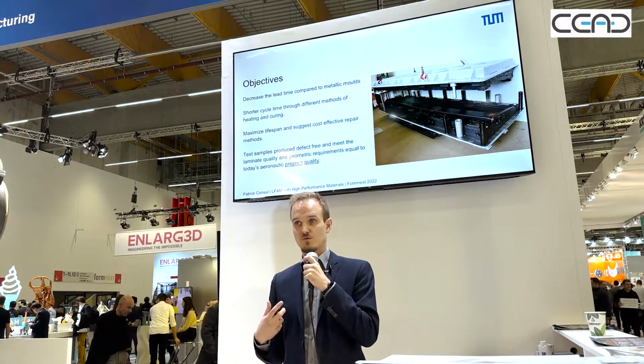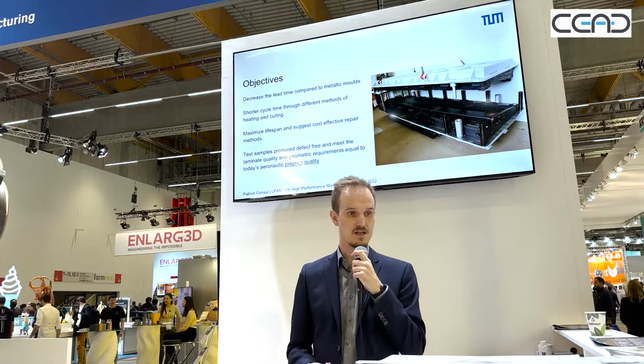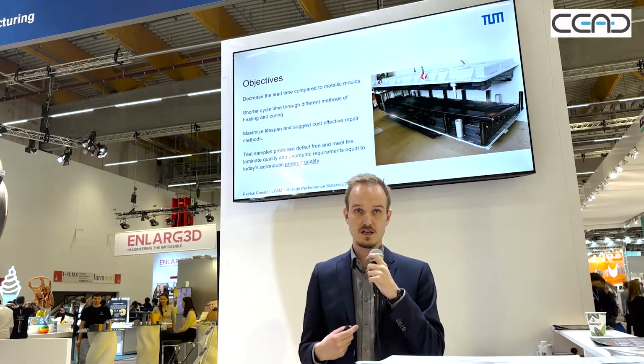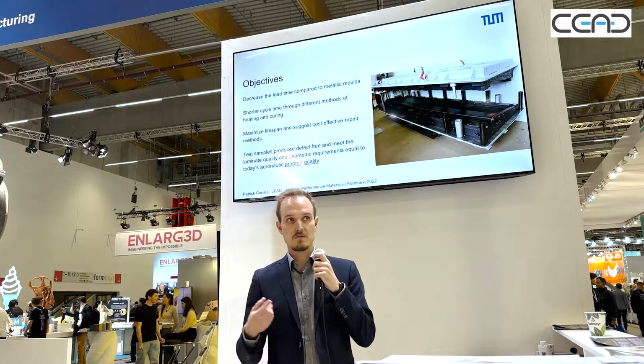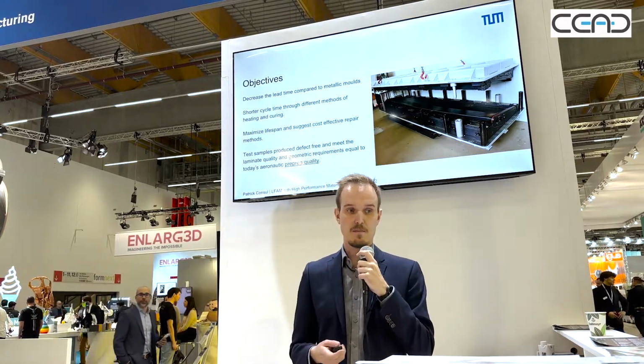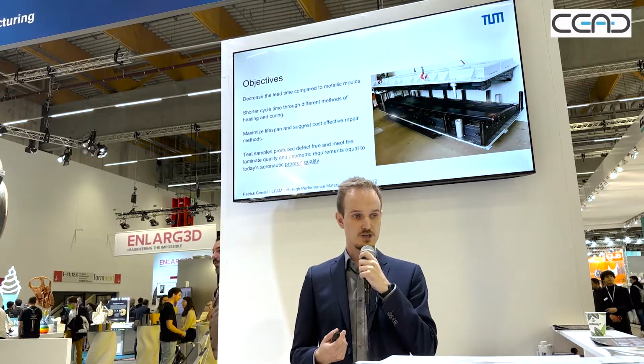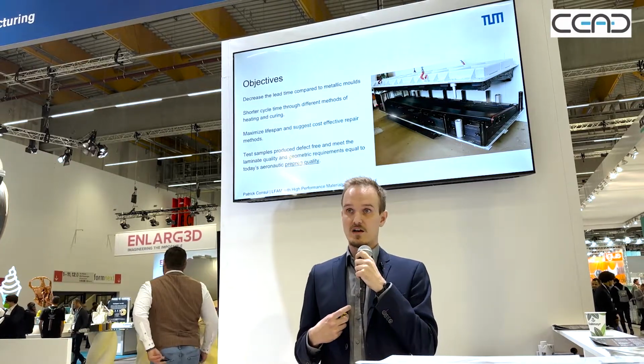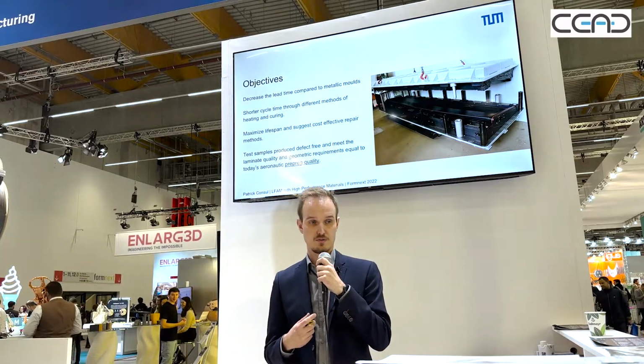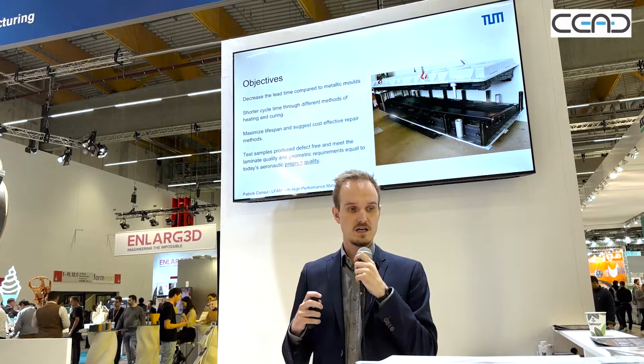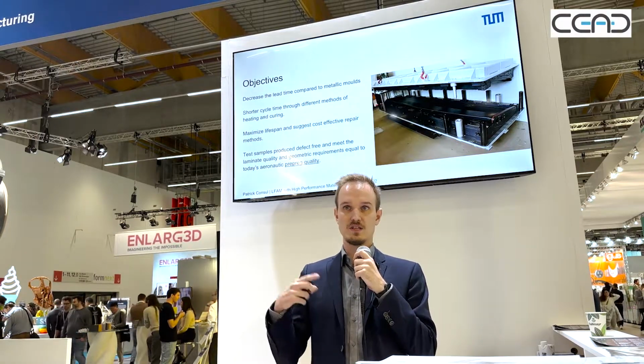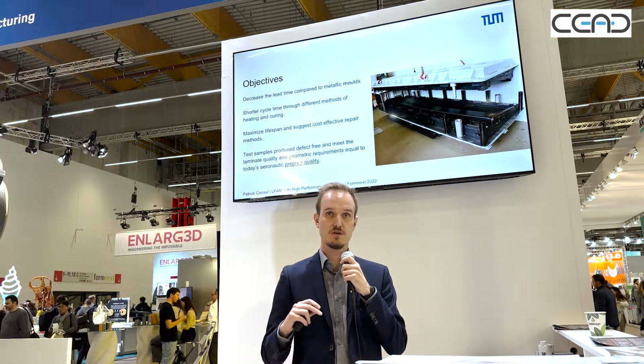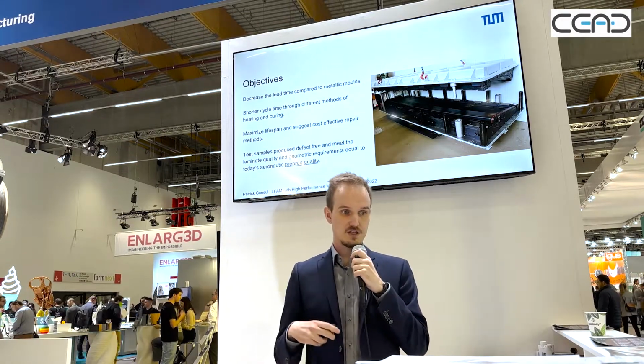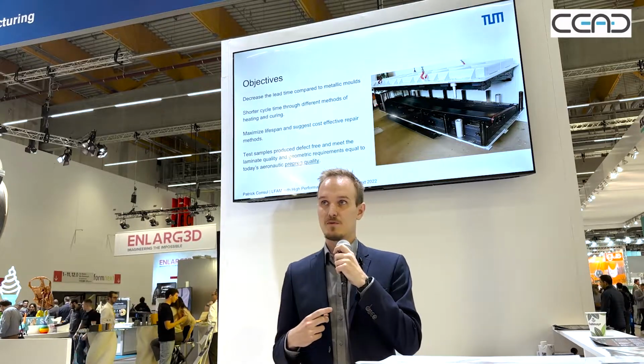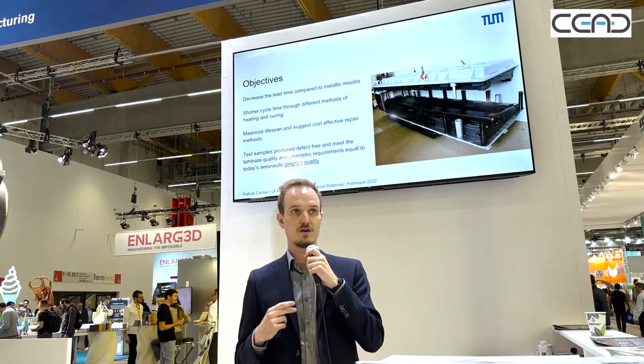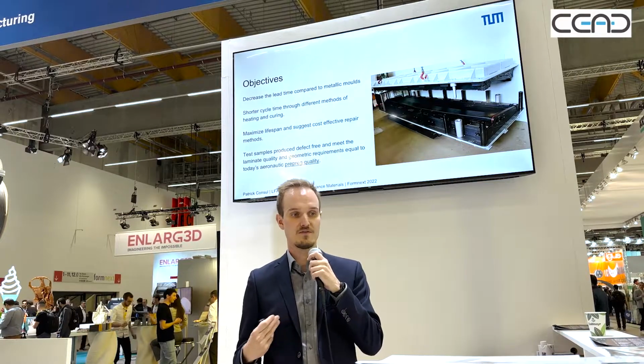Overall, the objectives as to why we would want to try and print a mold of this size was to decrease the lead time of these molds. They are usually milled from either aluminum or Invar, depending on whether it's a prototype tool or serial production tool. We also wanted to have shorter cycle times in composite production, and we wanted to achieve this by heating up and cooling down quicker by integrating cooling channels just below the surface of the mold. And a thing that Saab was quite adamant about is that they wanted it to have a lifespan as long as possible, so they wouldn't have to replace it all that often.